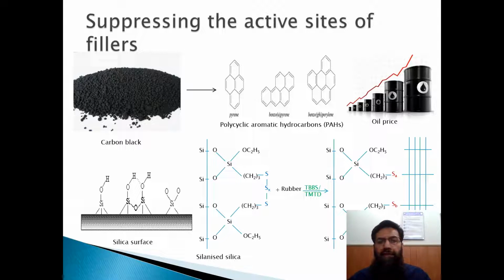And those chemicals are known as coupling agents, bridging agents or reinforcing agents. So what we do is we take the silanes and treat the silica with them, and those silanes actually react with the hydroxyl or silanol group, and when they react, they make a chemical bond with the silica, and now the active site would be that silane rather than the simple hydroxyl or silanol group on the surface.